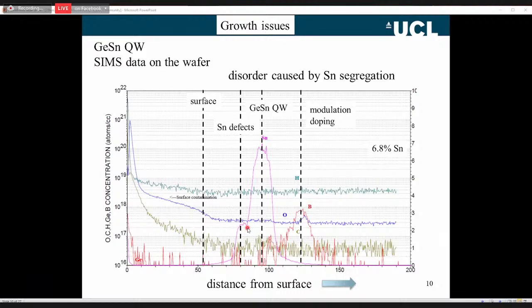So we thought it might form a double quantum well, so two quantum wells together with different tin composition. But now we think that the second tin layer just adds a disorder, a kind of disordered region. It doesn't actually form a quantum well, it just adds disorder, like scattering centers. That's why we think we see the localization effects, these scatterings. That's why the layers go very resistive. Yeah, this is interesting because there is another quantum well close. Exactly.